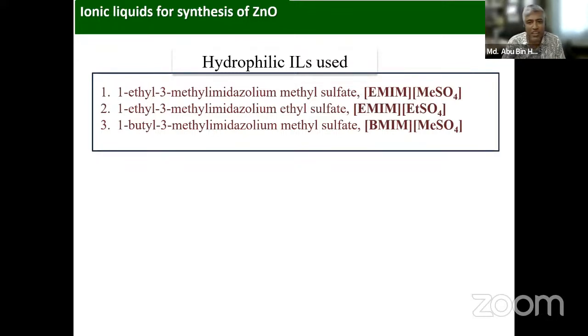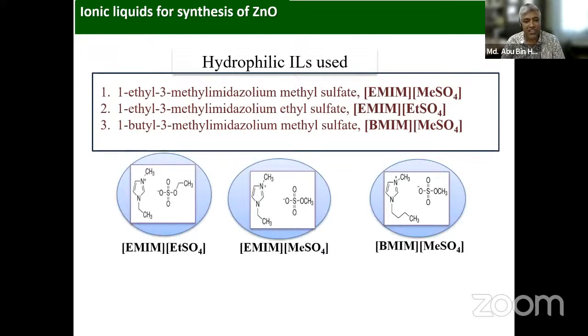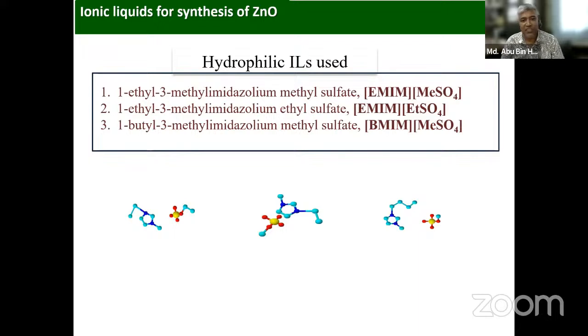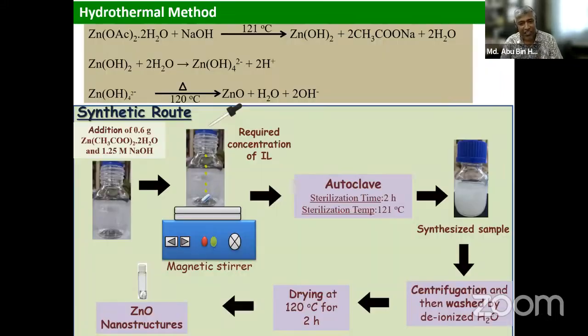We have used 3 different ionic liquids. All are hydrophilic ionic liquids. You can see 1-ethyl-3-methylimidazolium methyl sulfate, here ethyl sulfate, and we have also changed the cation to 1-butyl-3-methylimidazolium, keeping methyl sulfate common. These are the structures. And if we see the models like this, we can see that we can use these ionic liquids for preparation of zinc oxide by using the common hydrothermal method.